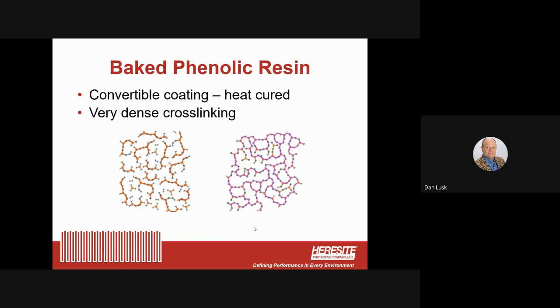So our baked phenolic resin, again, it's a convertible coating where it's baked in an oven. And it's a very dense cross-linking material. So if you look at the left side of the screen, you'll see the molecules when it's air dried. And then on the right side, you'll see how those molecules really come together and cross-link when it's heat cured and put in an oven.